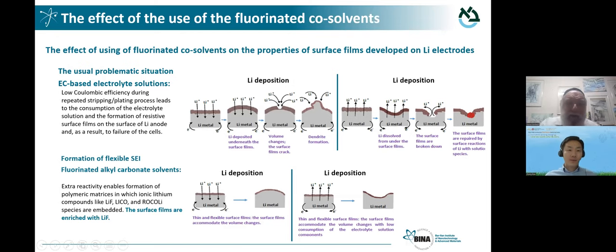So, what is the situation? Actual situation. We have SEI, but it's not flexible. It cannot accommodate either the deposition or the dissolution. So when we have lithium deposition or dissolution, the surface film cannot accommodate the morphological changes of lithium. So we have a break and repair mechanism, and we have side reactions between the electrolyte solution and the active metal.